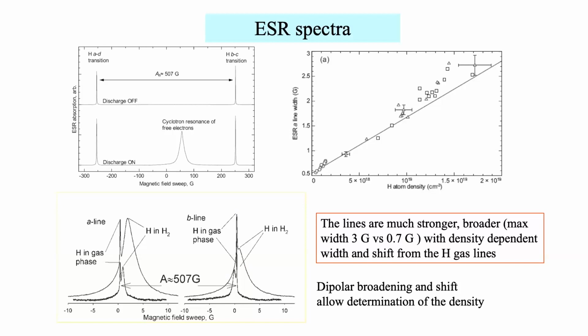At the beginning of the experiment you have a narrow line. This shows the signal from the atoms in the gas phase, and the broader line is the signal from H and H2. As time progresses, the signal becomes broader and shifts, and from this broadening we can determine the local concentration.